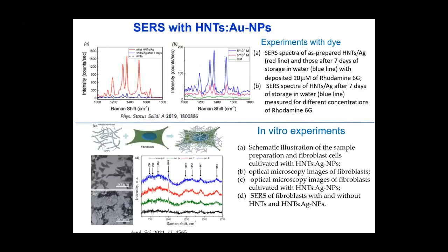This modeling was experimentally verified in vitro with model biomolecules — specifically dye molecules of rhodamine 6G. We observed the SERS (surface-enhanced Raman scattering) effect for halloysite nanotubes with deposited silver nanoparticles. Very importantly, the effect was stable for up to seven days of storage of such nanocomposite in water. Stability is a big problem for silver-based materials, but for these nanocomposites, they were very stable over a long time.